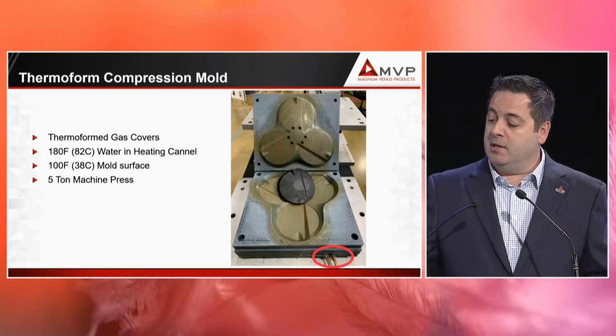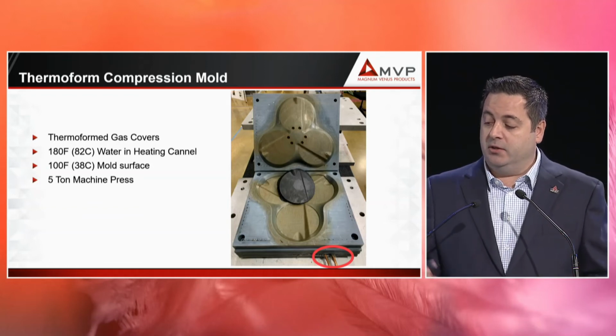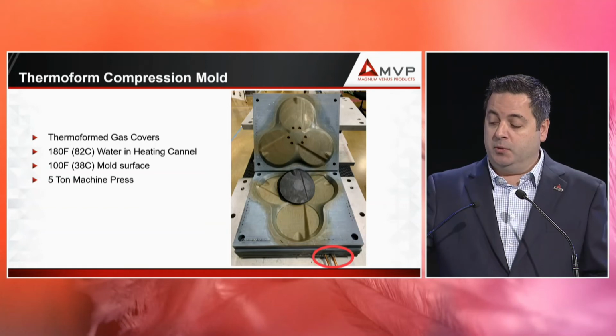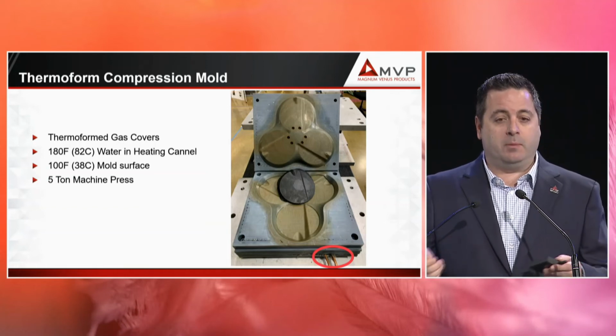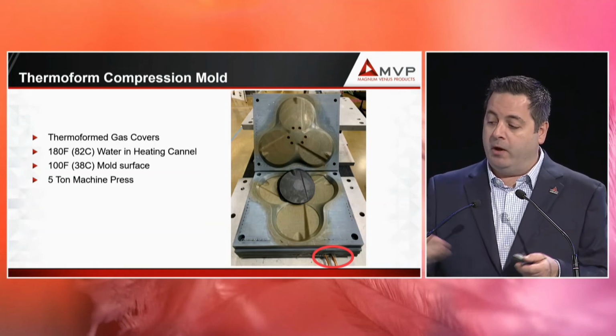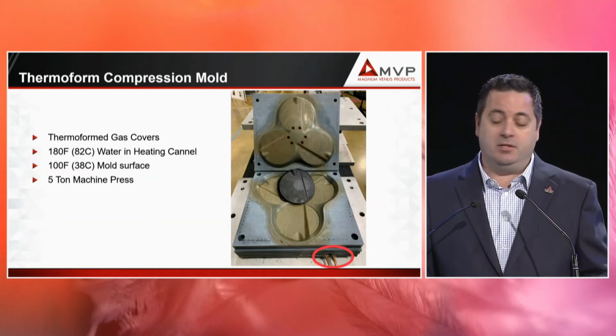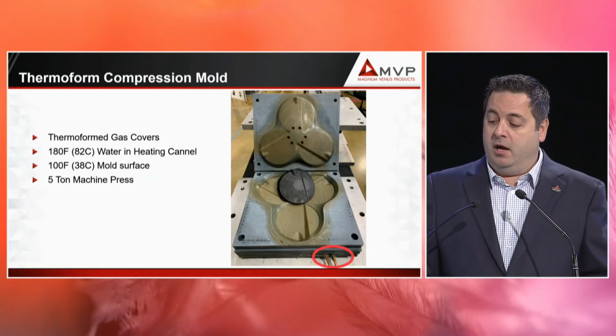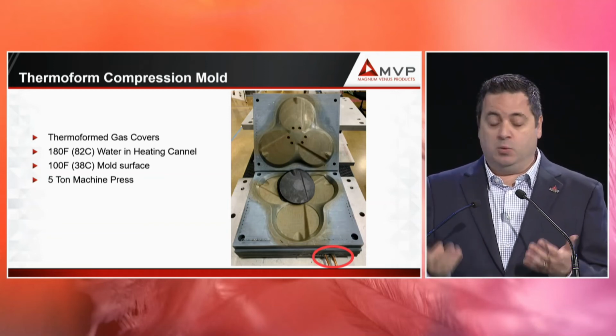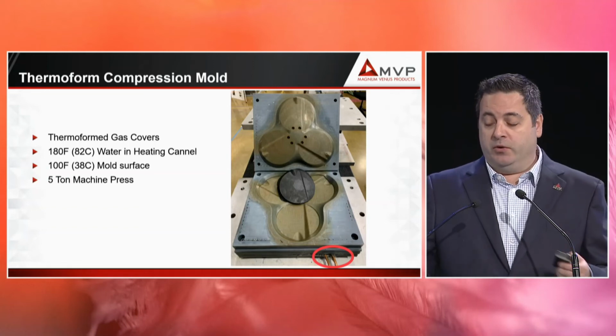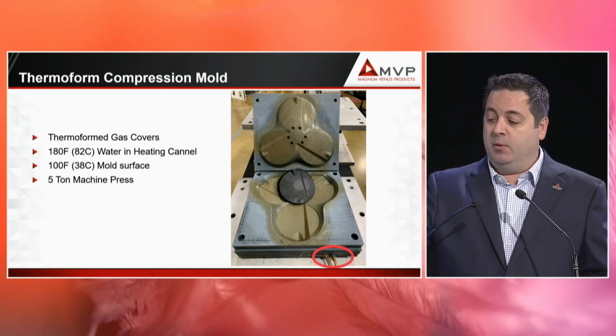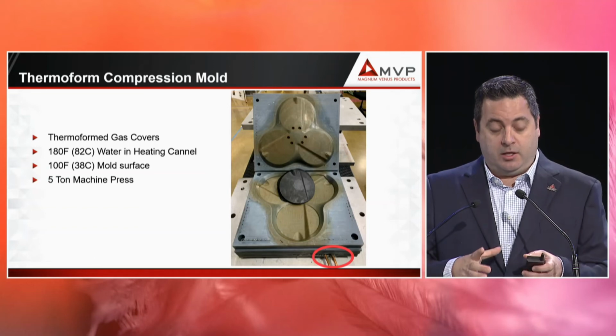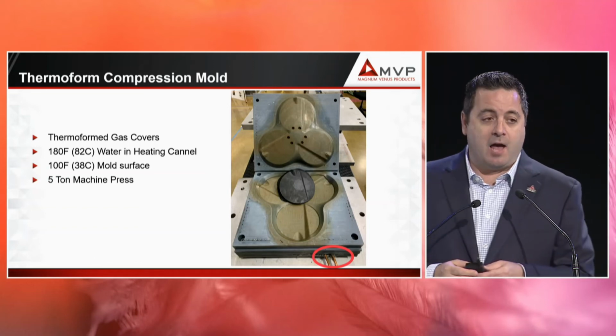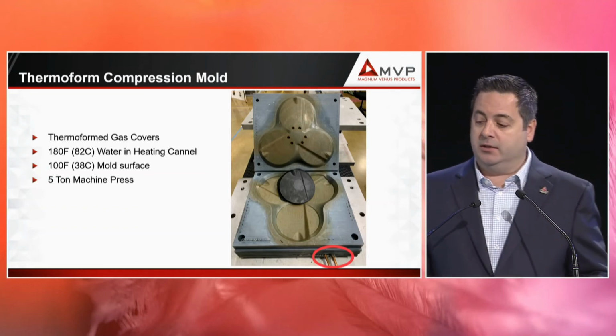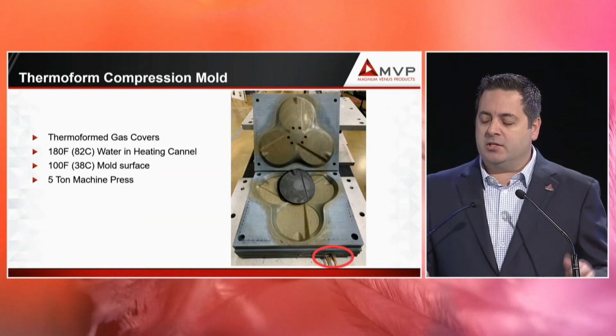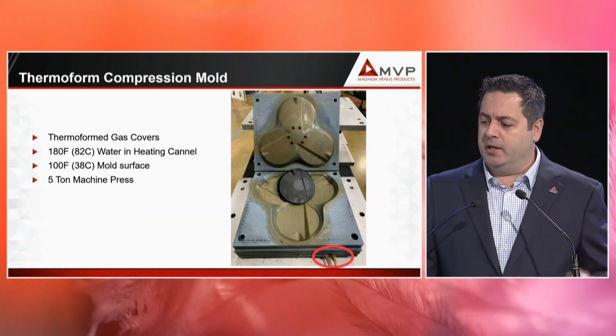And you can see in the bottom right where there's a red circle there, some heating channels were placed into this mold during the print, as we showed in the video of foam going, and in this one copper tubes were added to it. Water at 82 C was added to warm the mold. The mold surface actually saw about 38, and we used pre-preg carbon, and this is a gas cap. And that was again cycled. I think the cycle time on that was around 3 minutes.